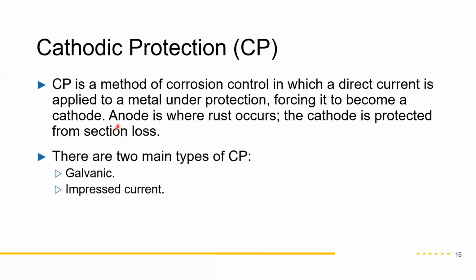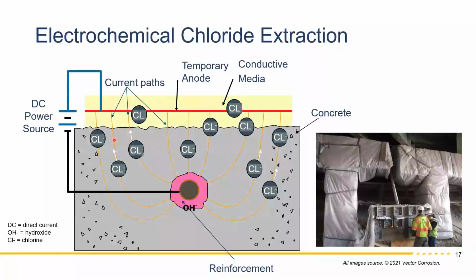The most common one is cathodic protection, where you inject a direct current to the corroded metal, which is the rebar, and essentially turn it from the anode, which is where the rust occurs, to a cathode. So you're sending a current, and at that point the corrosion process really stops. There are two ways of doing that: one is impressed current, and the other one is galvanic, where you put a sacrificial element on the pier itself that would preferentially corrode. This is very important protection, especially in a marine environment, aggressive environments. Especially down there in Boston, that might be an option to stop the corrosion from occurring any further.